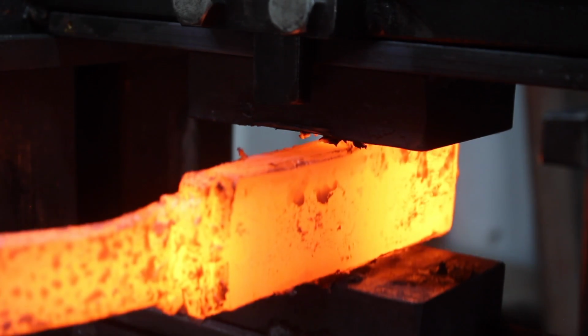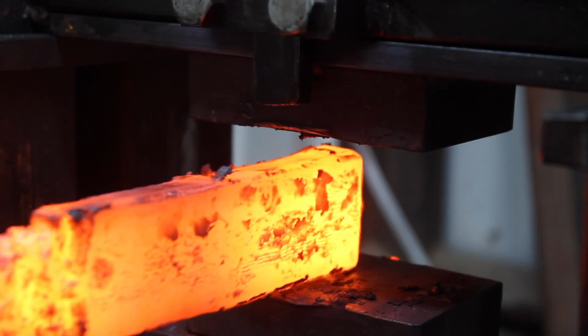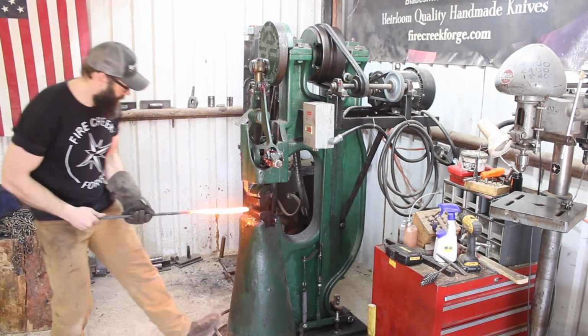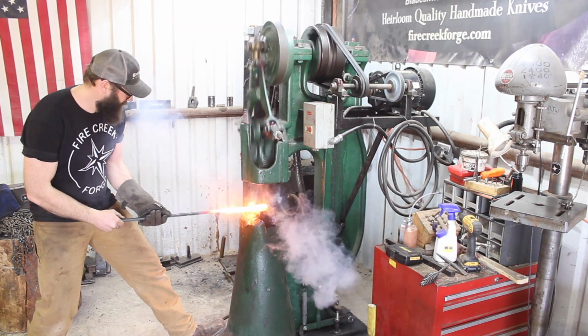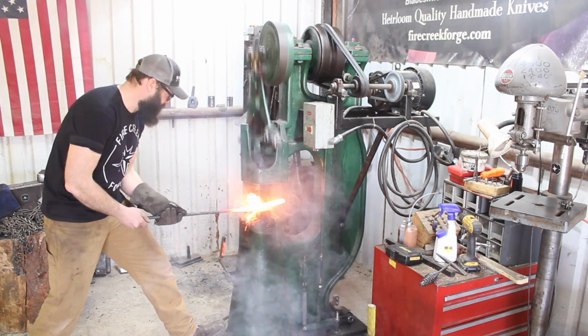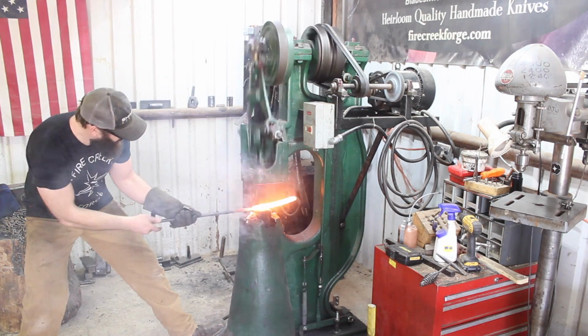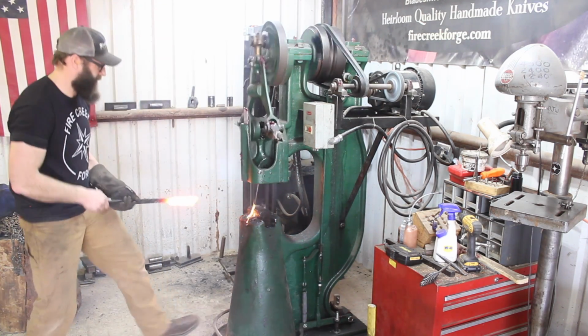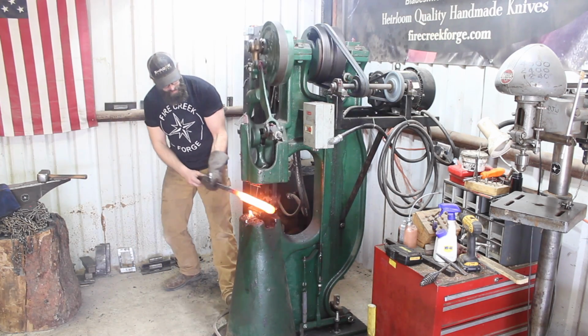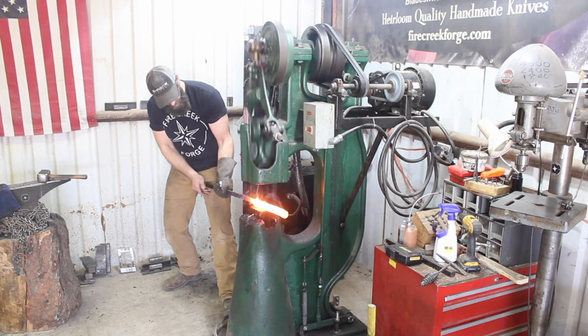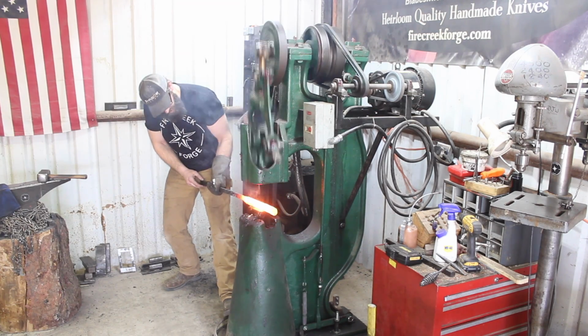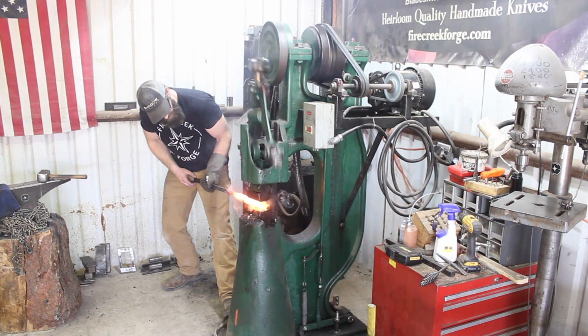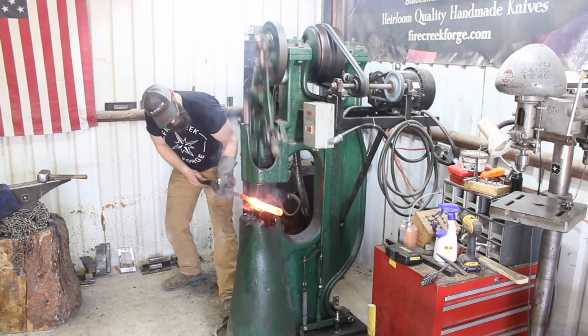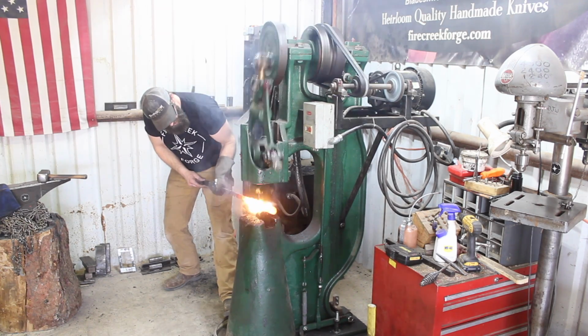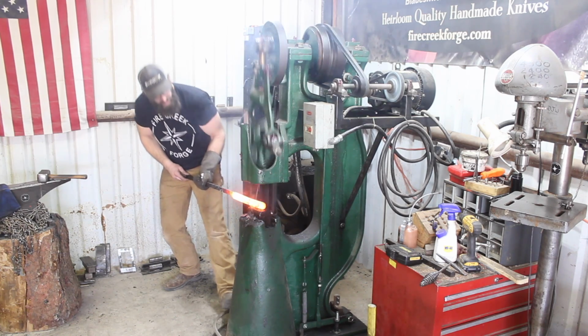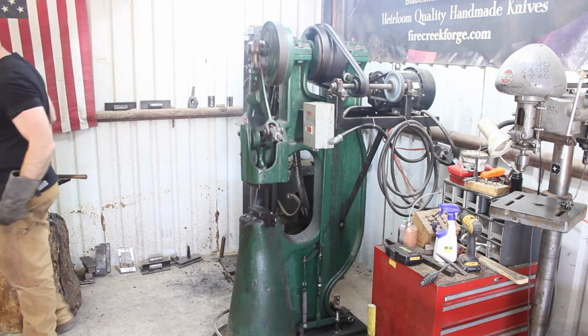So we have our Sanmai forge welded together, and now it's time to work this into a blade. So I went so far in the forging press, and up to now the 50-pound Little Giant has been left out and is probably crying in the corner. But this is where the power hammer begins to shine. Once you get down to those thinner cross sections, and we're still probably about 7/16 of an inch, I think, maybe half an inch, the power hammer allows you to work the steel longer because it does not suck out the heat the same way that the forging press does.